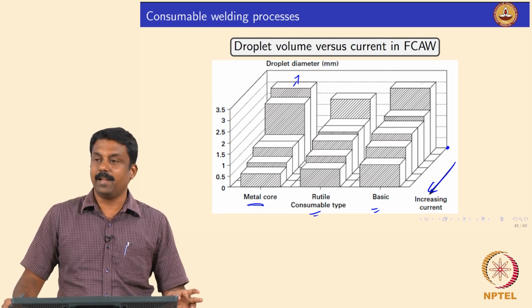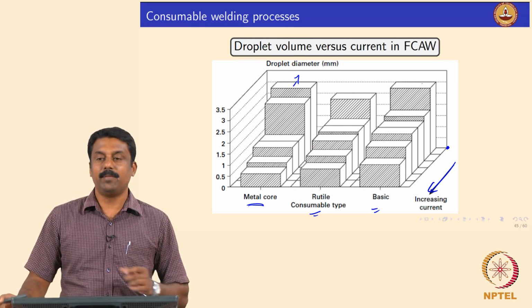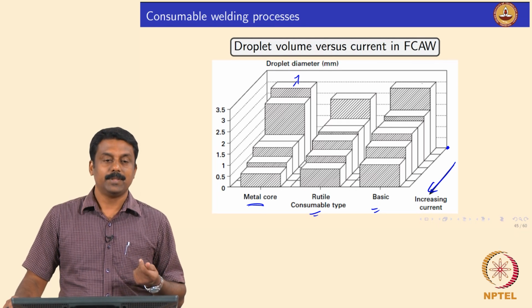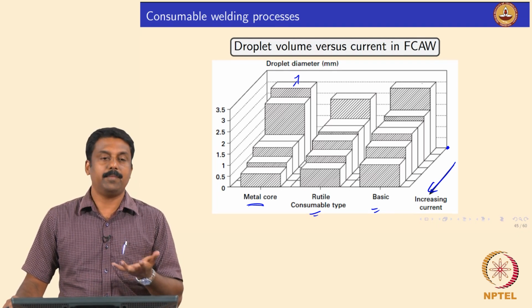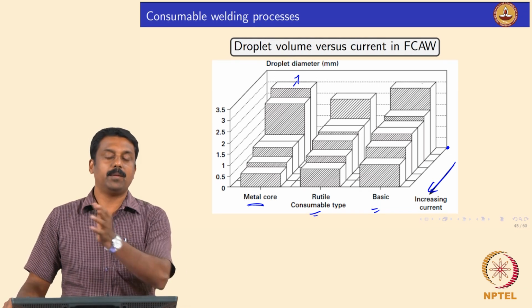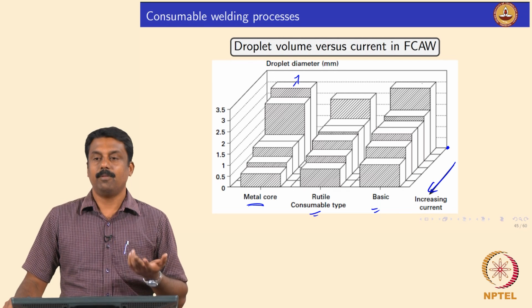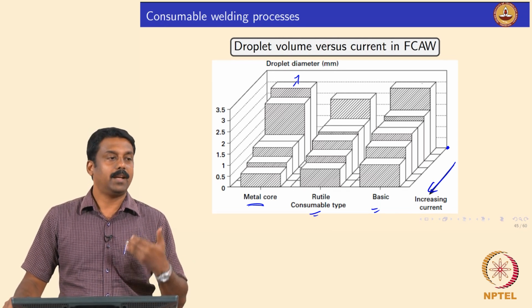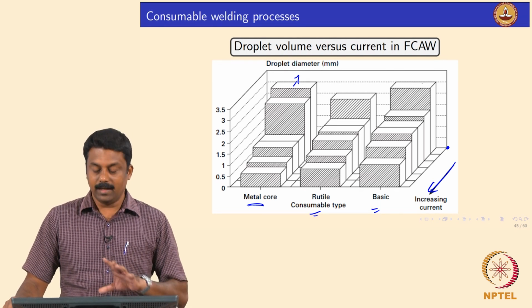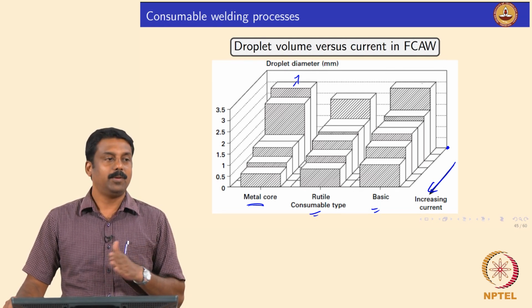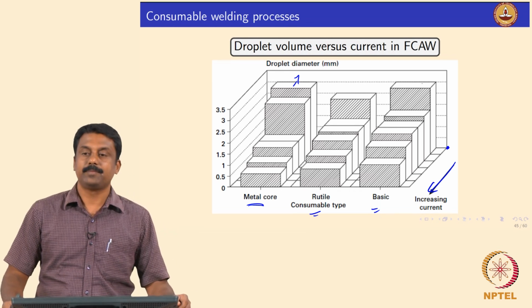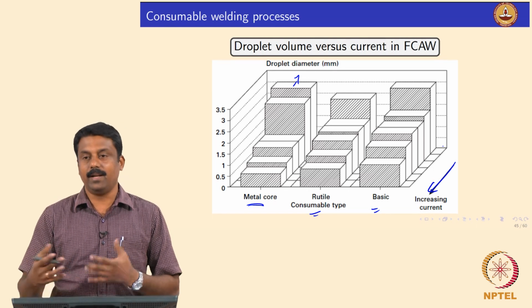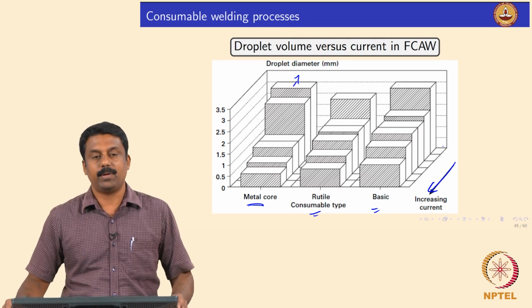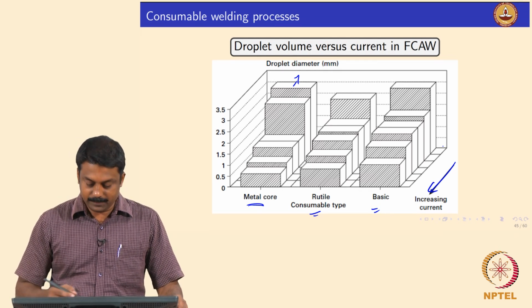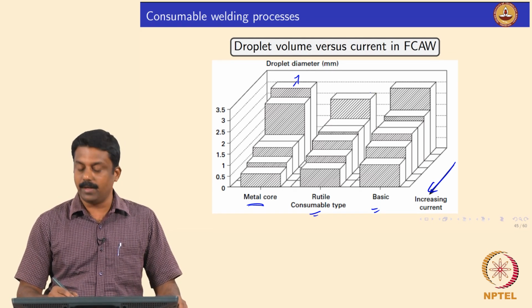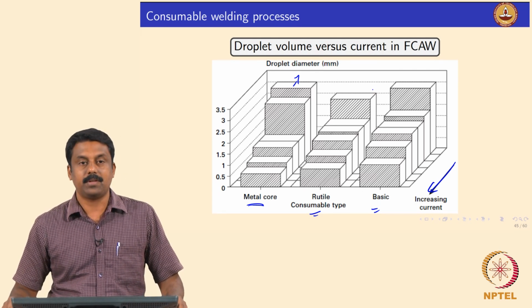But then if you add fluorides and silicates, there are other complications. So now you have to play around with the flux chemistry. So you can think about adding titanium oxide, but the hydrogen should be pinned by some other elements, like for example boron. Okay, so we can also form boron hydrides. It can be removed as a slag. So then systematic studies should be done to achieve the required droplet transfer. Once you understand the science behind the process, then we can tackle very common day-to-day problems. Right. So it's clear. The rutile based consumables always give a smaller droplet diameter because of the reduction in surface tension of the droplet.